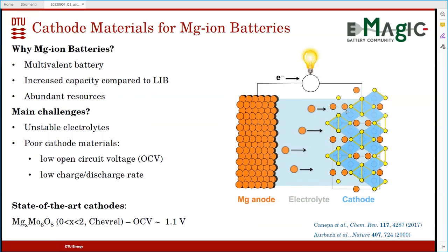And this is taken from cathode materials for magnesium-ion batteries. Why magnesium ion instead of lithium? It is multivalent, has an increased capacity compared to lithium, and has much more abundant resources. But then we have unstable electrolytes, and the cathode materials have a low open circuit voltage and a relatively bad discharge rate. Now, the open circuit voltage here is 1.1 volt compared to 3.7 of lithium-ion batteries. I take the example from magnesium ion, but the method is general. Everything that I show you today is chemistry agnostic and technology agnostic.